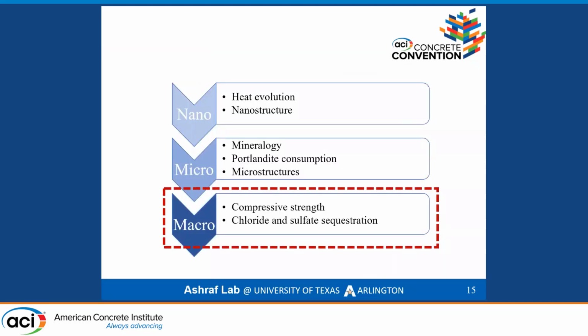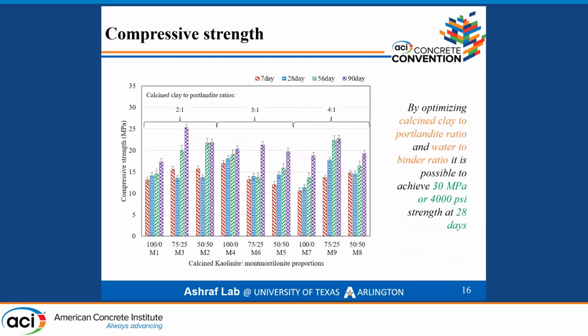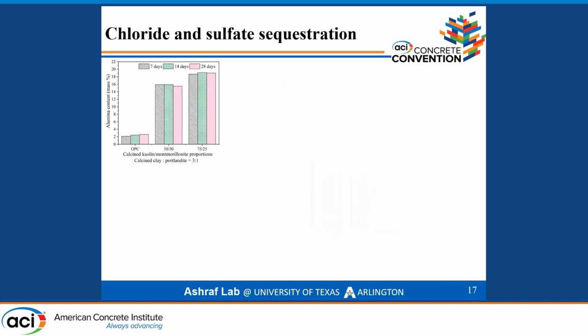So let's talk about the macrostructural properties. This is the compressive strength data of our samples over 90 days of curing age. We got our highest strength for the M3 batch at 90 days, which is 25 MPa. However, 30 MPa concrete can be achieved at 28 days with this type of material by optimizing the calcined clay to Portlandite ratio and the water to binder ratio.